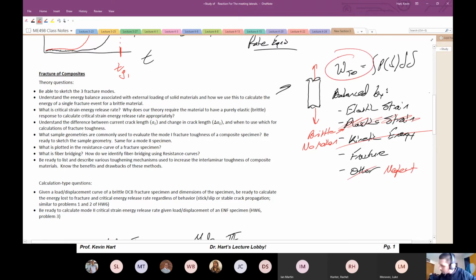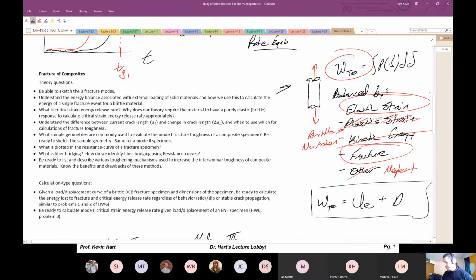And so really, the total work that we put into the system, we said was going to be balanced by elastic strain and by fracture. So mathematically, we wrote that the total work that goes into a piece is the elastic strain energy UE plus the energy associated with fracture, which we labeled as capital D. So this was the general model and where we built everything for composites in our particular class. This was the basis for all of the modeling that we did for our system.